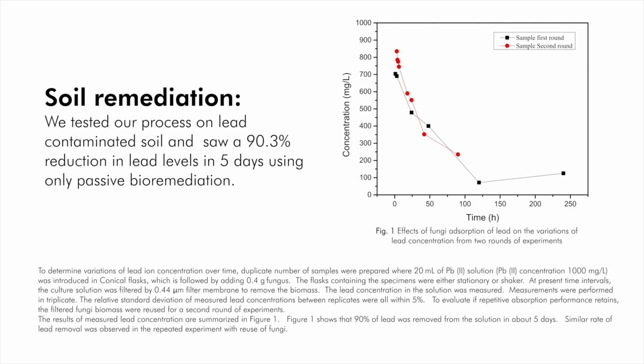Another test that we did with folks at Case Western Reserve looked at having that mycelium in an aqueous slurry. In that one, we were able to remove 90% of the lead in just 5 days.